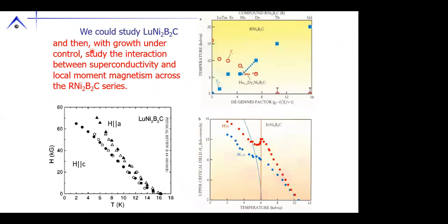And if we studied it, we could see that it indeed has a TC around 17. It has a fairly isotropic HC2, but a rather low one. So this was sort of disappointing for applied superconductivity. On the other hand, if you can form something with lutetium, you can usually form it with the other rare earths. And indeed, thulium, erbium, holmium, dysprosium have coexistence of superconductivity and local moment rare earth magnetism. And these materials became a playground for understanding the interaction of large local moment magnetism with superconductivity. It's sort of the opposite extreme of the magnetic superconductors we see in the cuprates or in the iron-based materials.